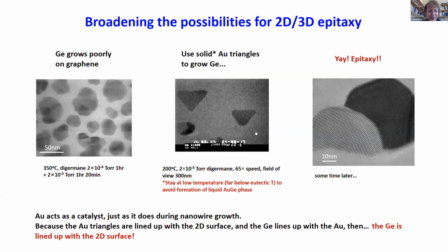How about we grow germanium on a 2D material? Well, it doesn't work very well, but we know that gold works very well. And we also know that gold is a good catalyst to grow germanium nanowires. So if we combine these two ideas together, we get a movie, which is, I have to say, not my most exciting one, but look here.